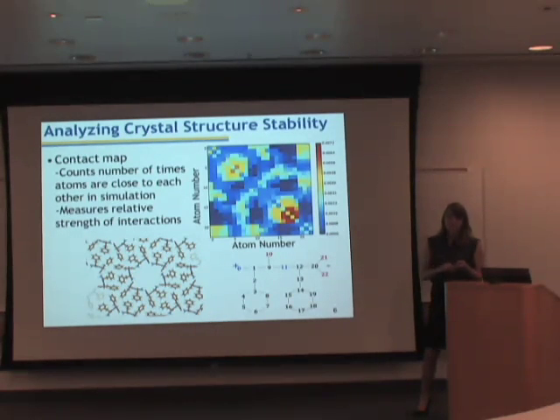Where blue numbers represent nitrogen atoms, black numbers represent carbon atoms, and red numbers represent oxygen atoms. Looking at the contact map, interactions are rated on a scale of red to blue, with red being the highest amount of interaction and blue being the lowest amount of interaction. The first thing we wanted to do was use this technique to look at the crystal structure and evaluate the places in which we saw the most interaction in the crystal structure. The first thing we wanted to look at was this hexagonal pore. It has previously been suggested that this is the first motif seen when